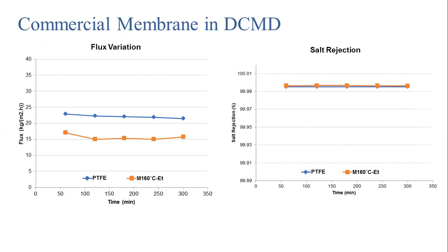Yes. Basically, PTFE is a polymer called polytetrafluoroethylene. This polymer is extremely hydrophobic and has a very good tensile strength. This is a commercial membrane that we have bought, and we have done a benchmarking for it. It showed a very stable salt rejection and very stable flux. We at AUB tried to mimic this.